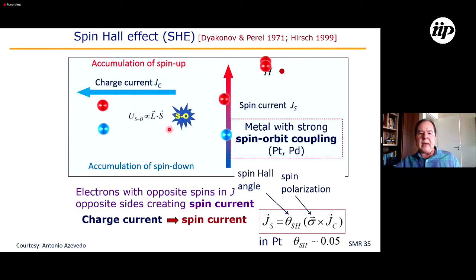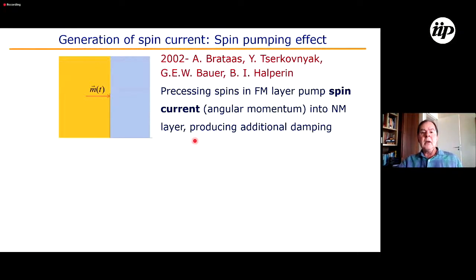Platinum, which is a metal with large spin-orbit coupling, has a spin Hall angle, the coefficient of this conversion, which is 0.05. Some complex materials have a spin Hall angle of 0.5. 0.5 means 50%. So it means that of all the electrons in the current, 50% go up and 50% go down. Well, in 2002, these gentlemen made another theoretical prediction.